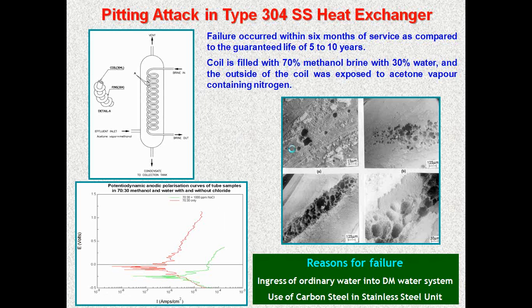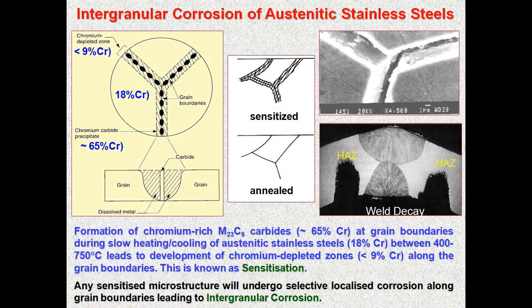Intergranular corrosion is another important type of corrosion of austenitic stainless steel, which happens in a sensitized structure. You see the grain boundary is selectively attacked, particularly in a welded component. In the heat affected zone very close to the weld area, the corrosion attack is due to the sensitization.